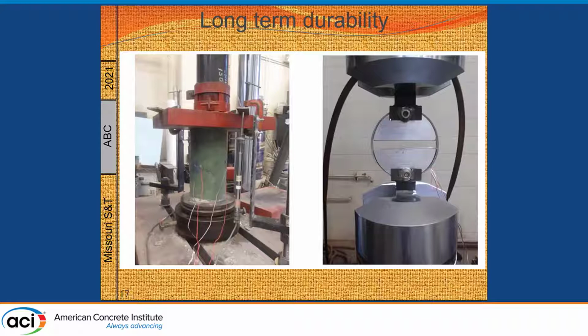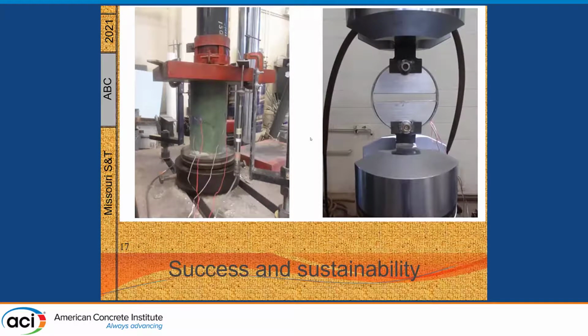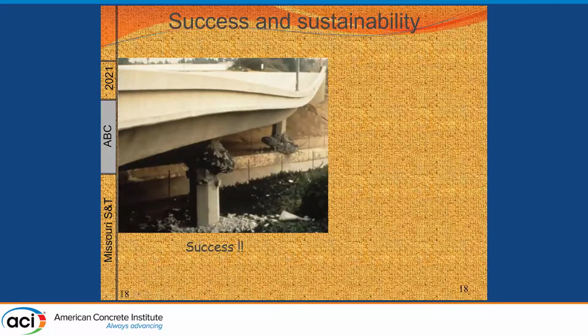For other specimens, we knocked the concrete out and cut the FRP cylinder into rings. You see the rings over here, and we did a tensile test on the FRP rings. So this was some research on the columns, working also with hollow core columns.